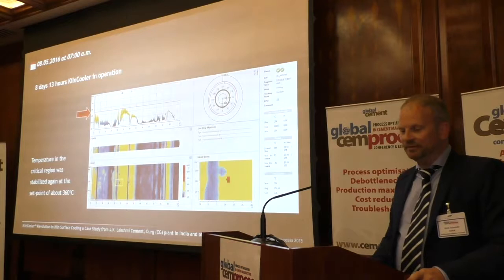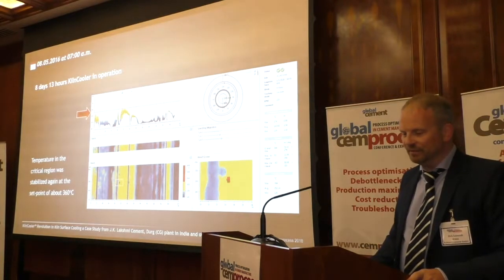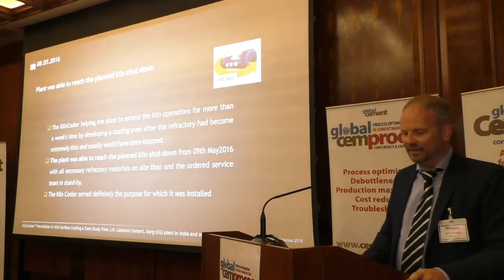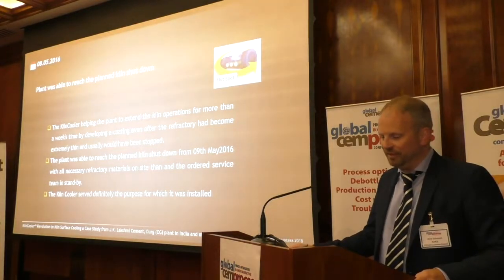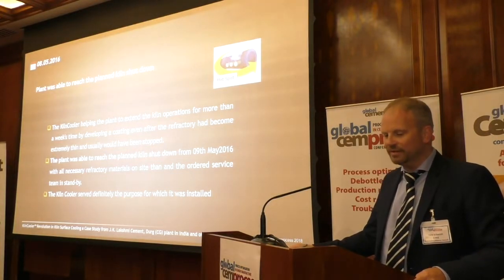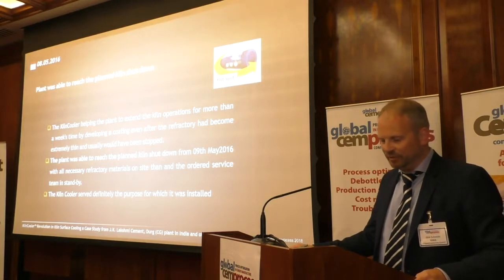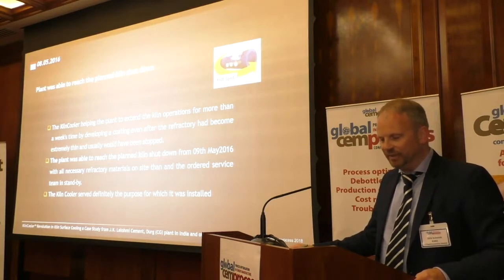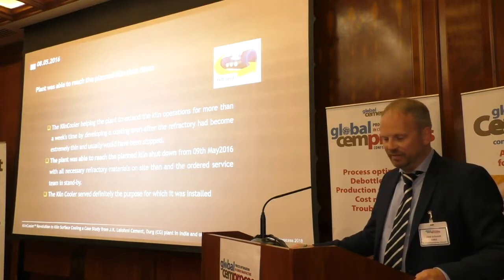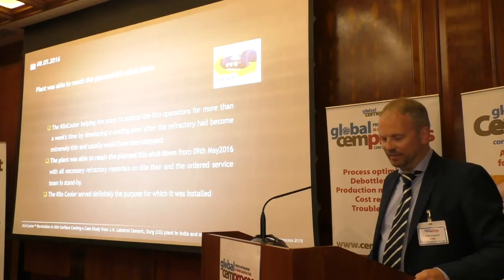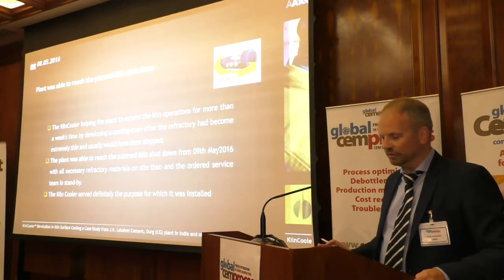At the end, after 8 days and 13 hours, the customer was absolutely satisfied and said the KilnCooler was helping the plant to extend the kiln operations for more than a week's time by developing a coating even after refractory had become extremely thin and usually would have been stopped. The plant was able to reach the kiln shutdown on 9th of May with all necessary refractory materials on site and ordered services on standby. The KilnCooler served definitely the purpose for which it was installed.